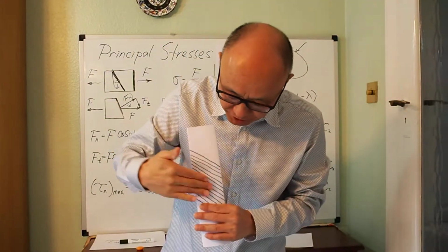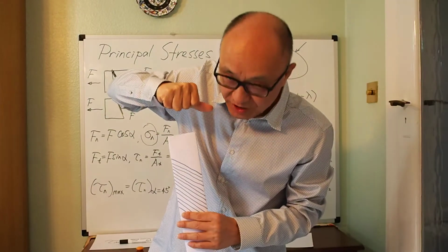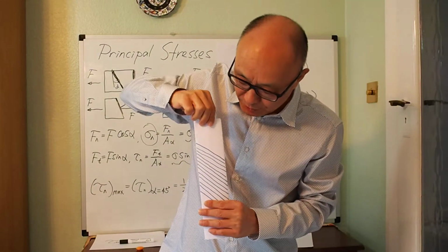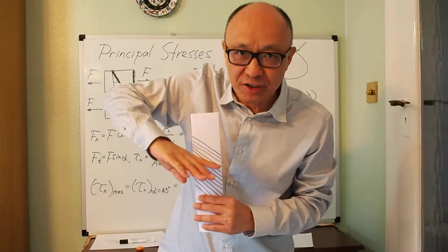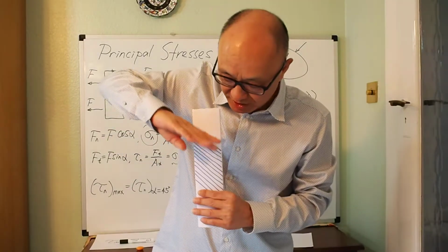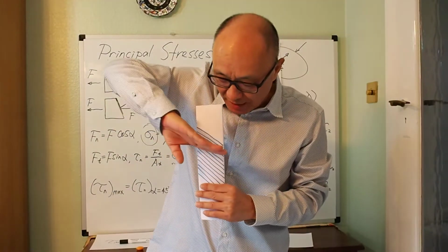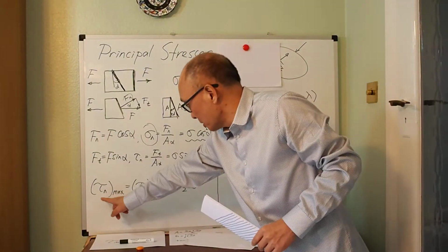If you polish the surface and apply force and then reach the plastic deformation range, you see these slip bands forming, and you can actually observe them. The surface becomes rough, and you see these slip bands, and they form at 45 degrees because of the maximum shear stress.